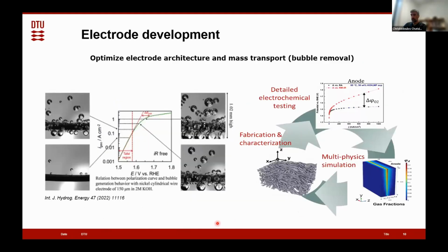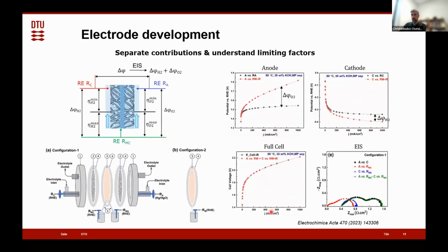Now, besides coatings, it's also very important to develop electrode architectures in order to get good electrode performance. And here, mass transport and ease of removal of bubbles is very important. And we try to approach that by combining detailed electrochemical testing with multiphysics simulations and the characterization of the fabricated electrodes. With respect to the detailed electrochemical testing, we have developed a novel method to analyze the electrochemical response of a cell at zero gap configuration.